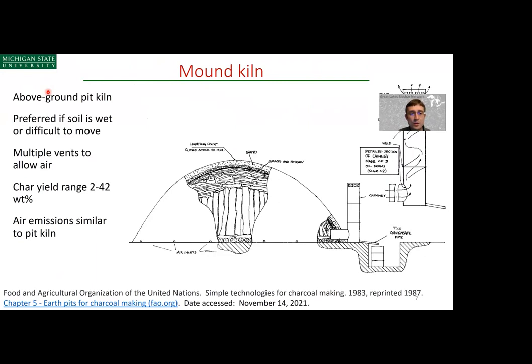If the soil is wet, or just difficult to dig into, you can essentially perform the same type of pyrolysis in a mound kiln. This is just an above-ground kiln, shown here in a depiction. In the mound kiln, we typically leave a number of air inlets down below, and those air inlets can be plugged once the pyrolysis is ignited and slow pyrolysis is occurring. Char yields from these mound kilns tend to be in the 2 to 42% range. This is actually quite a broad range, but mound kilns are inexpensive to build.